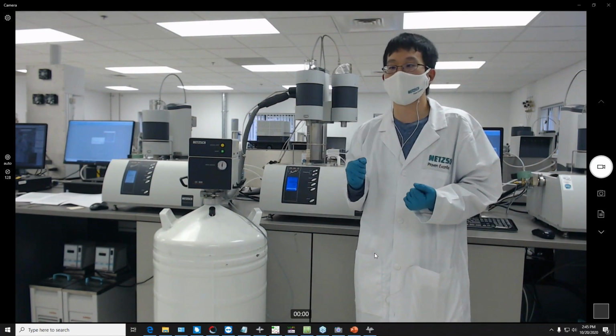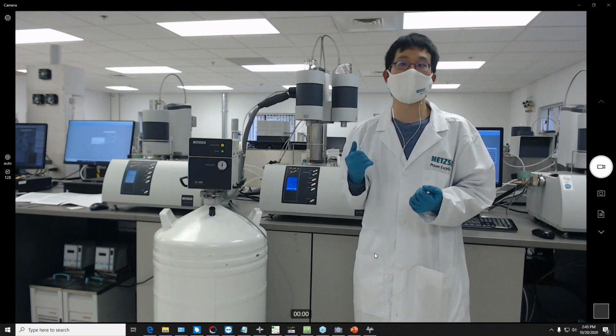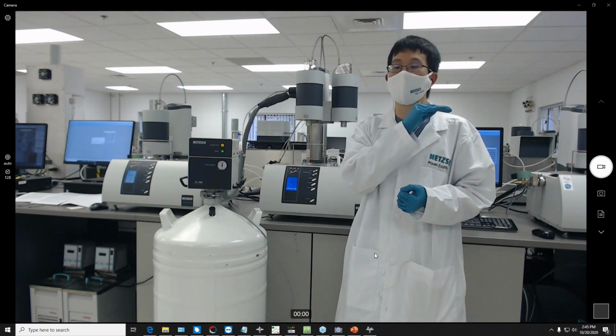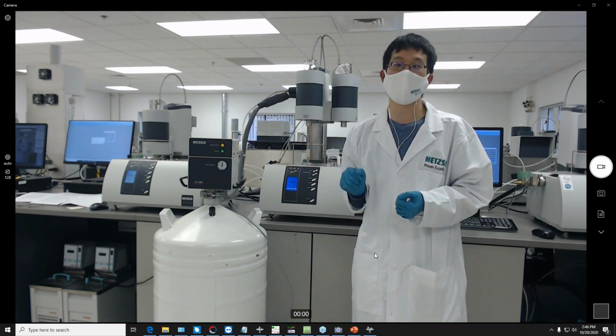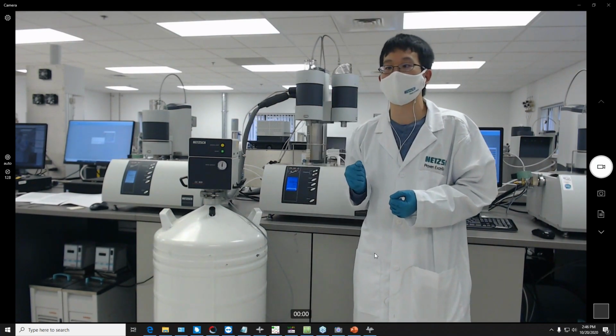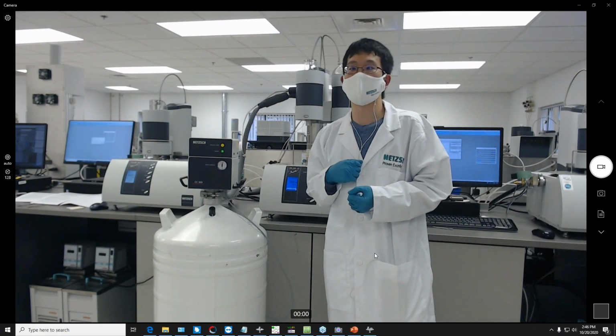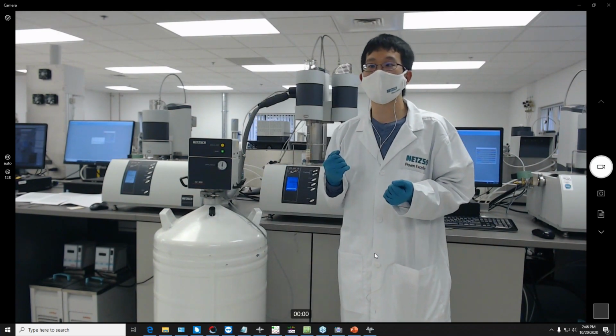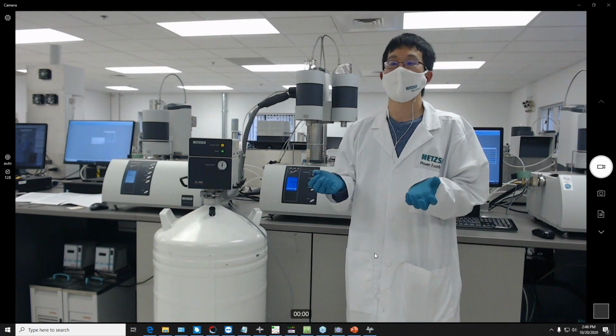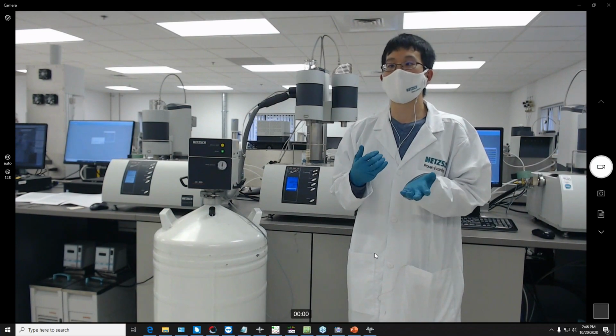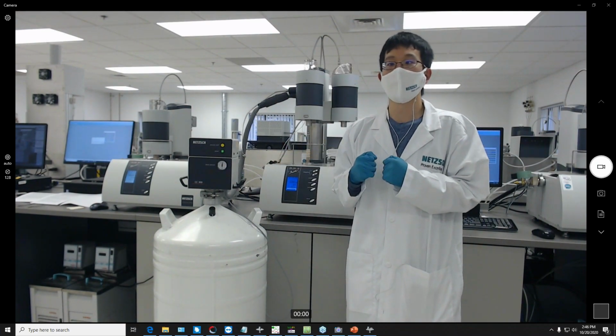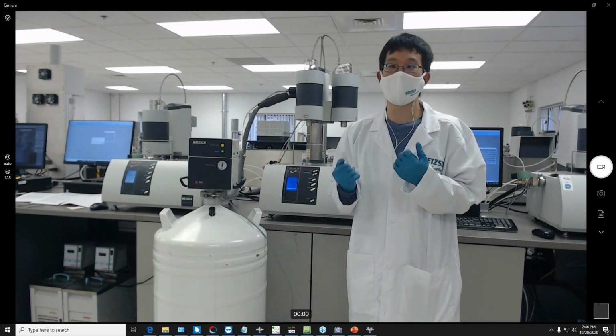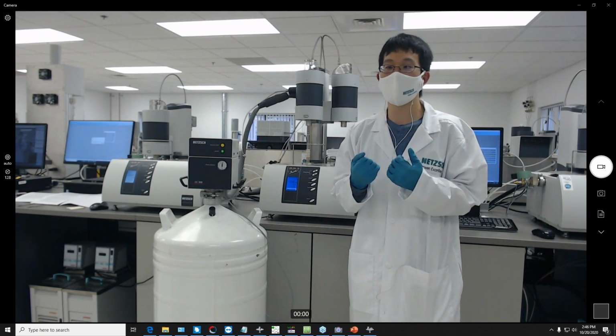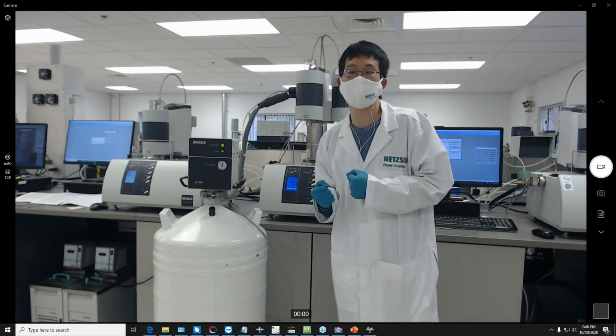When we go to, let's say, hold that isothermal at a specific temperature, so I ramp and go to 1,000 degrees C, and I want to hold my sample at 1,000 C, then we can do the isothermal with the 1,000 and then turn the STC on, to make sure that our sample stays at 1,000 degrees C. So usually that would be the case when I turn STC on and off, if I want to hold my temperature at a specific value. And then during the linear heating and cooling ramps, I'll turn STC off.